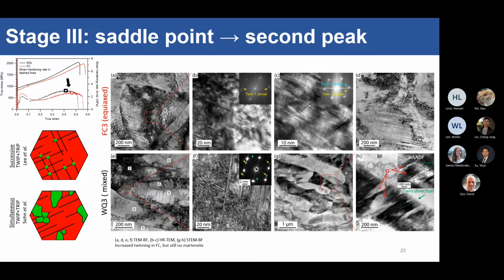So the carbon content of these steels is extremely important. Carbon has the largest effect on the stacking fault energy of the austenite phase. Your epsilon martensite forms when your stacking fault energy is too low, so it forms epsilon rather than twins. But epsilon martensite doesn't really give you a lot of strength.